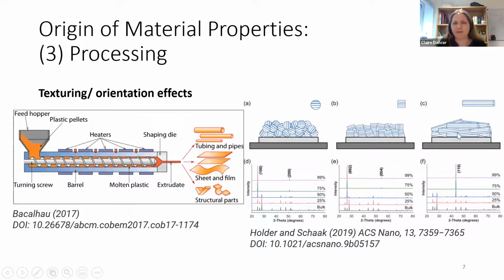But I think it's quite interesting to look at these top images and see the crystallographic planes being represented within the particle. If we have these spherical particles which are just allowed to fly down and scatter, you get quite a random orientation. Once we start to confine the shapes and make more blocky grains, here drawn as a square, in practice a blocky cuboid-esque thing, you can start to see that you're going to get some preferential alignment, and the vast majority of these are aligned along the surface. When we go to tubular or wire-like structures and we deposit them, it's even worse, and we always see texture in those kind of materials. And often it's the sort of texture we don't necessarily want. We don't want them all lying down like this. We probably want them sticking up, and that can be quite challenging to pull off. Generally, if you want to influence that and change it from the natural effect, you need to use an external field of some kind to generate some ordering in the structure.